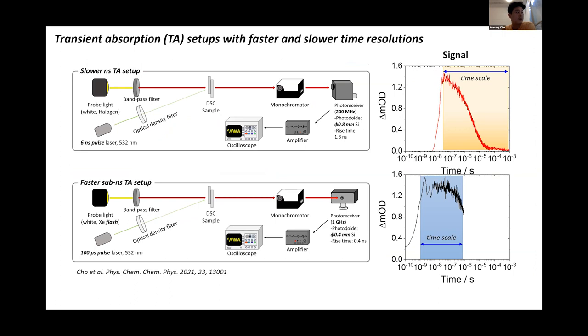So the question is, what would be the impact of the time resolution of the transient absorption setup, which is often used to measure this electron transfer kinetics. Transient absorption, a time-resolved spectroscopic technique, is often used to determine charge transfer kinetics. Take the upper setup, called the nano TA setup, which has a few-nanosecond pulse laser as a pump. With it we can measure decay on a 100 nanosecond to millisecond time scale. With a faster setup using a laser with a shorter pulse, here a 100 picosecond pulse laser, incorporated with some digitizers, it can measure transient absorption decay at the half nanosecond to 100 nanosecond level.